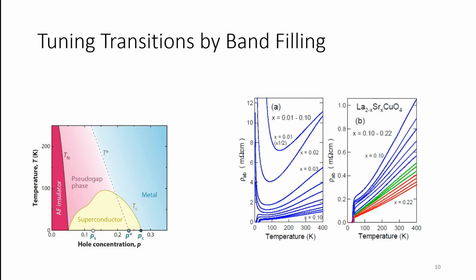And there are many other oxide systems where this trick is used to change the properties of materials. A very good example is the case of the high-Tc cuprate, for example this system here, lanthanum strontium copper oxide, it's a mouthful. By changing, again, the ratio of lanthanum and strontium, if you start off with just 0% strontium, the material is insulating. It has a high resistivity at room temperature, and when you reduce the temperature, this resistivity goes up to really large values.